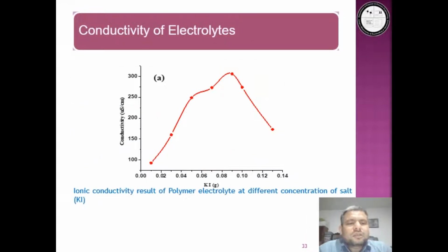Similarly, this is the conductivity curve. As you can see in the figure, the conductivity of polymer gel electrolytes increases with increasing the salt concentration. It shows the highest conductivity value of 300 microsiemens per centimeter at 0.09 gram of salt. However, it can also be observed that the conductivity decreases at higher salt concentration due to ion cluster formation. Saturated solution shows maximum conductivity as the concentration of salt further increases from the saturation limit. It will not dissolve and remain as a cluster, which reduces the ionic conductivity of the solution.